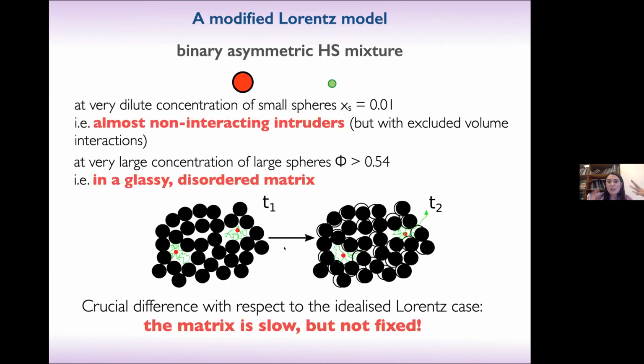So the crucial difference from the idealized case that we saw in the slide before is that in the Lorentz model you have a fixed matrix, and so the intruders, once there is percolation of the void, or there isn't percolation of the voids, can just move in the available space. However, when the matrix is glassy, the particles can at some point diffuse away, even if in some configuration the voids do not percolate. So there is this new ingredient, as well as the excluded volume interactions of the intruder with the matrix and with themselves, but they're very, very dilute.